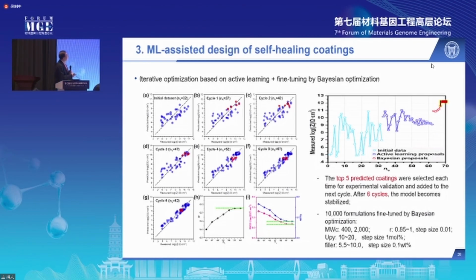5, prepared them, measured them, and fed back into the input side, and did this iteratively for 6 cycles, and the model became more or less stabilized. And then we did the Bayesian optimization, which literally can give us about 10,000 formulations. We can identify the best one. This is showing the evolution of corrosion resistance of the repair coatings from the initial 32, during the active learning, and eventually after Bayesian optimization.